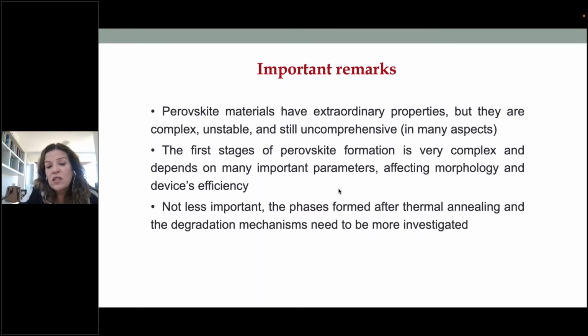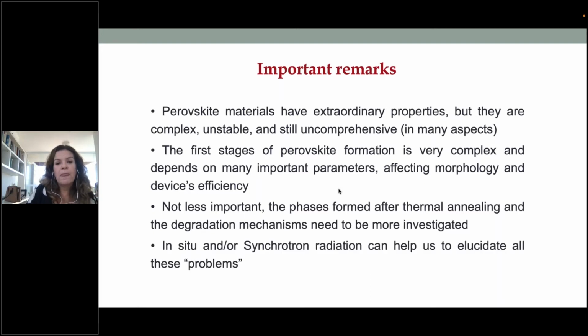Not less important, all of these phases that are more thermodynamically favored to form, we need to try to control them more, because recently we also demonstrated that these hexagonal phases are the first phase to appear at the beginning of the degradation. So we really need to study these hexagonal phases more and avoid them. And I hope that I have shown you here that in situ and or synchrotron radiation techniques can help us in some way to elucidate some of these problems.